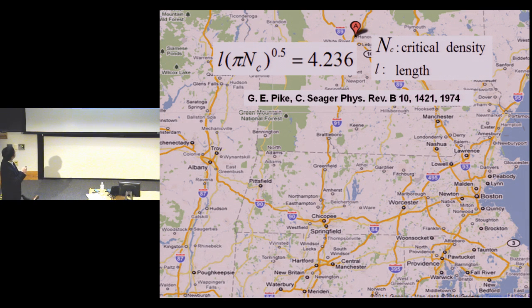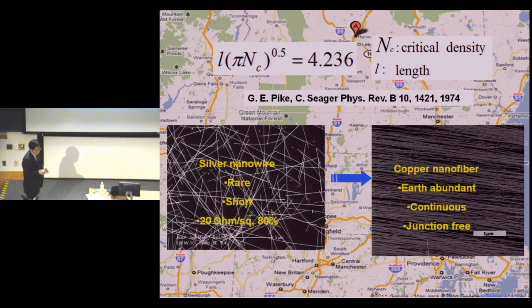Below a certain density, which is called the critical density, you will never get any connection from one place to the other. As you increase the density, once you reach the critical density, you reach the percolation threshold, and then you will get conduction from one place to the other. Of course, the critical density will depend on the length of the wire. So to decrease the percolation threshold, you would like to increase the length of the wire. This is basically the reason for the work on electrospinning continuous copper nanofibers. The idea is that instead of using silver nanowires with a certain length, I would like to use continuous fibers made of copper, which is much cheaper than silver as well.